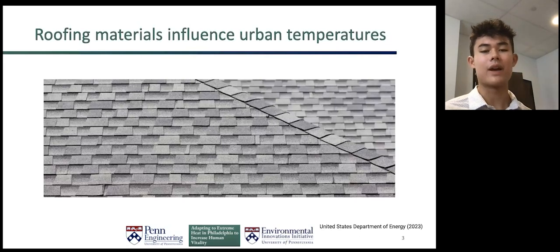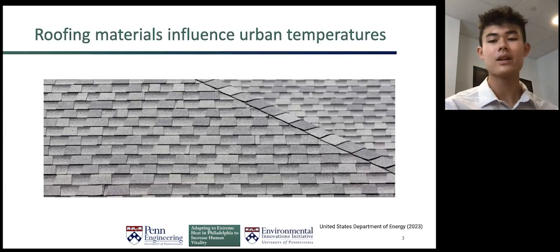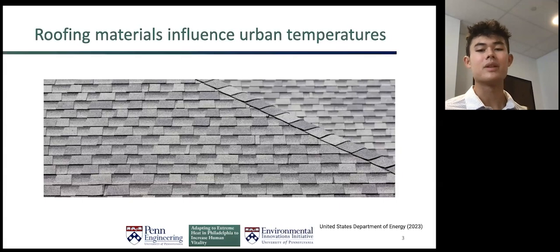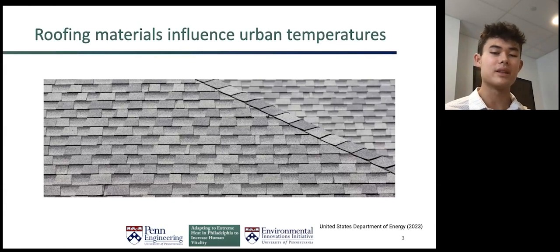And one of the biggest factors in this is roofing materials. So this image is an example of asphalt roofing tiles that are one of the most common roofing materials in the US and in Philadelphia, especially on residential buildings. And dark colored materials like this can easily get up to 50 or 70 degrees Celsius. And that can heat up houses and the surrounding cities to intolerable temperatures. So it's really important to replace materials like these with other cooler alternatives.